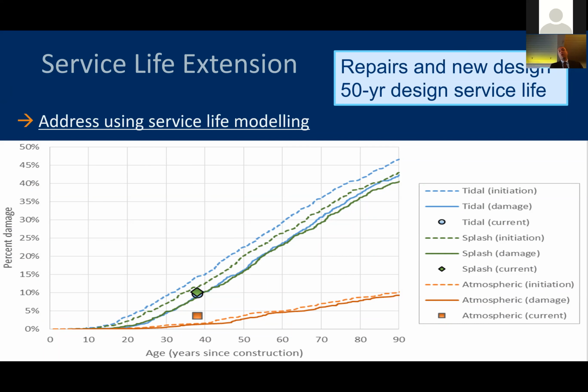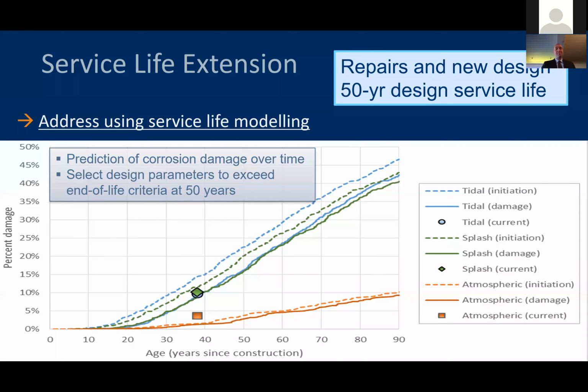And so you can see from this curve, these are looking at existing elements. Those orange lines represent the atmospheric zone, and going 50 years into the future, it's going to be less than 10% damage. So that's an example of something that doesn't really need to be repaired, whereas the things in the tidal and splash zones will be well above that, and currently are, based off the corrosion and damage that we were seeing already. So we were using our field data to calibrate our models and then estimate forward.